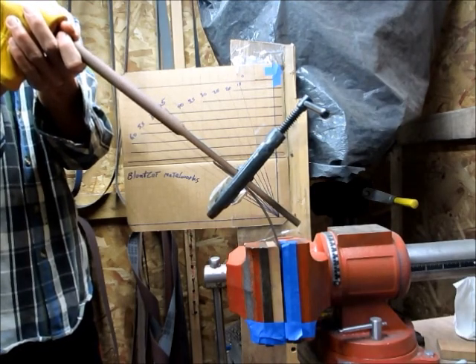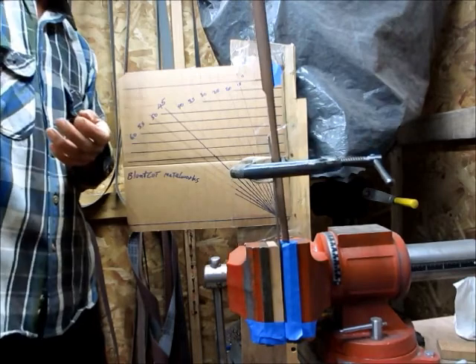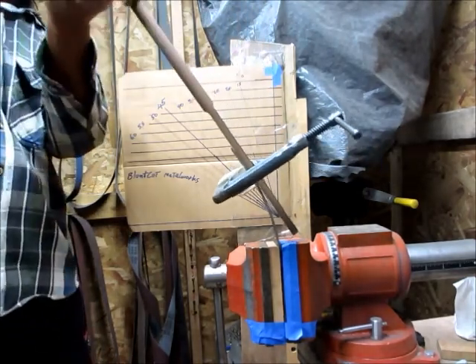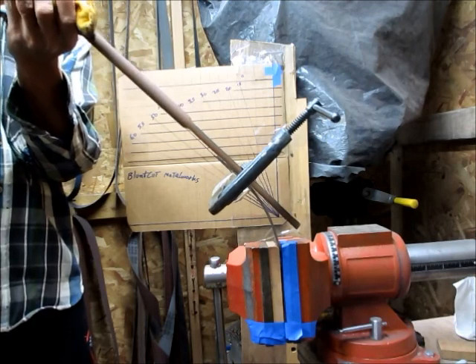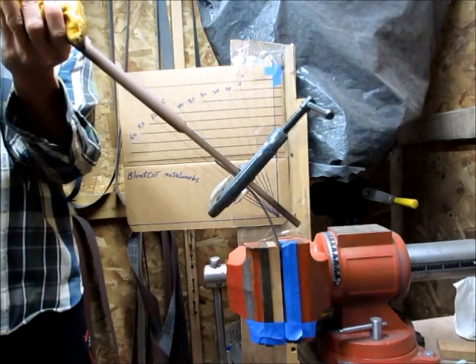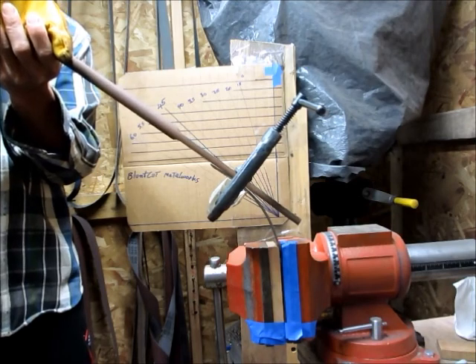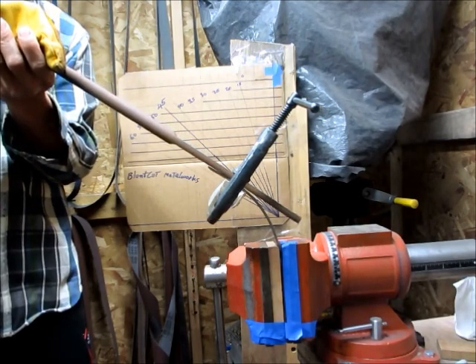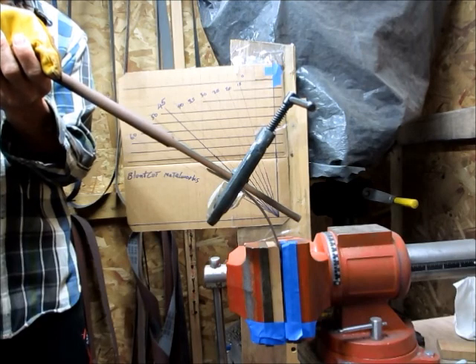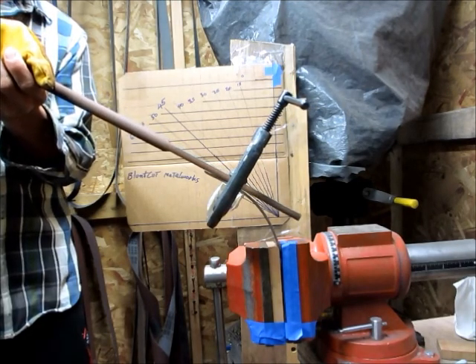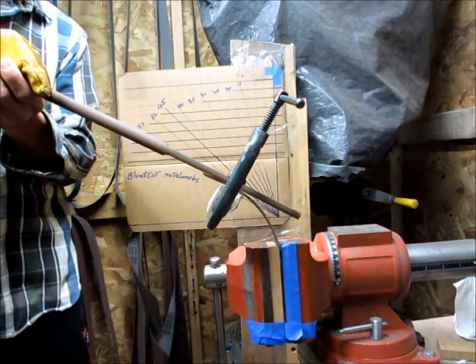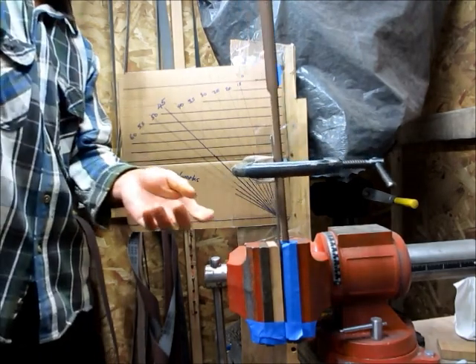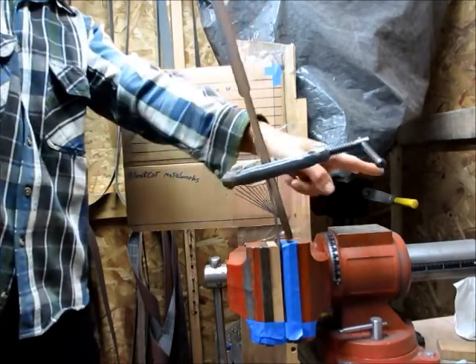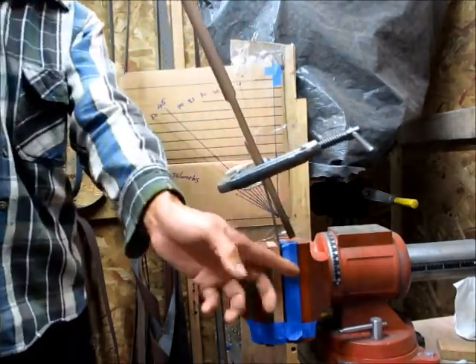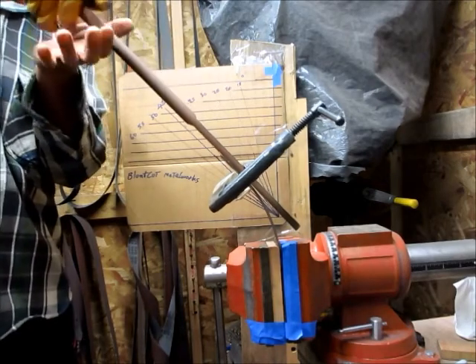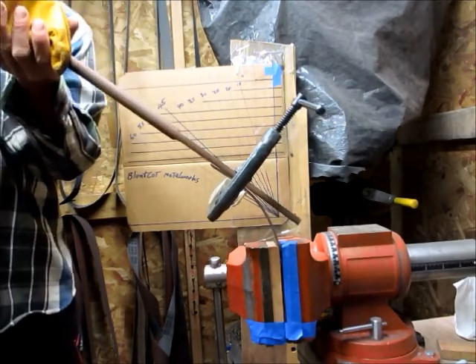When you have a blade and the geometry changes, the edge gets cooled very fast, and the spine cools down a lot slower, so you have inconsistent hardness. To measure the angle, it's pretty much this length. The bar had a point here, and the angle again vertical here, and so you can calculate the angle of bend for this fairly short piece.